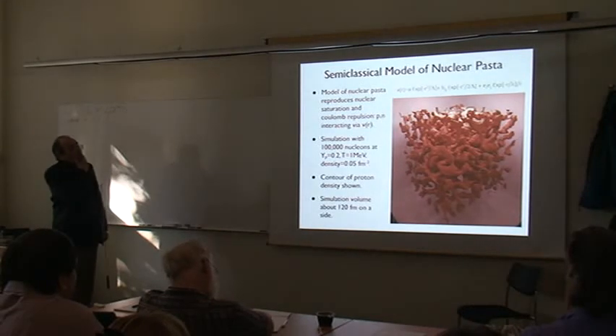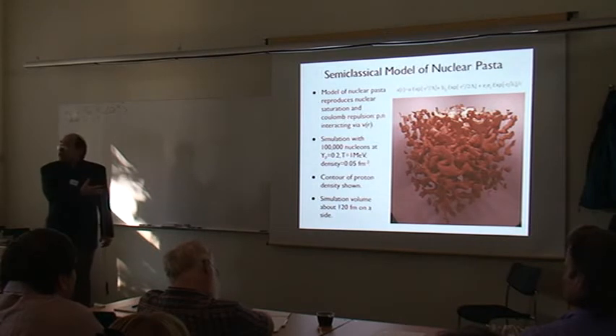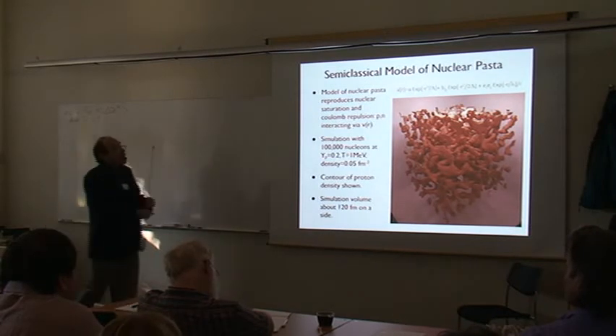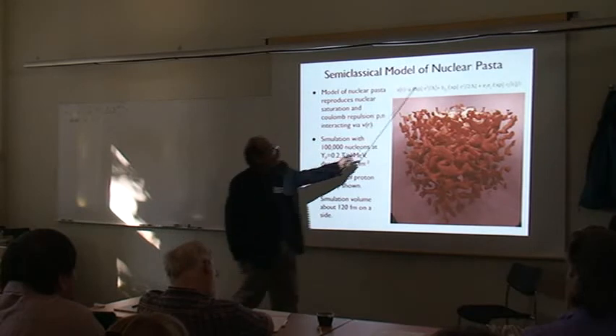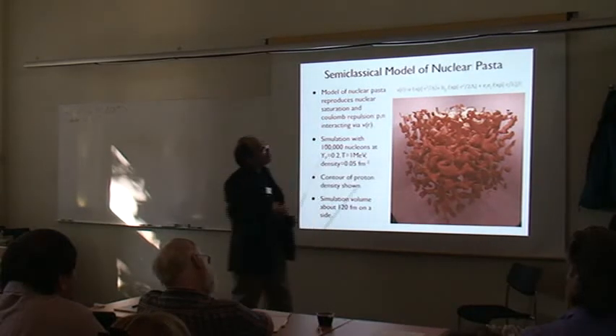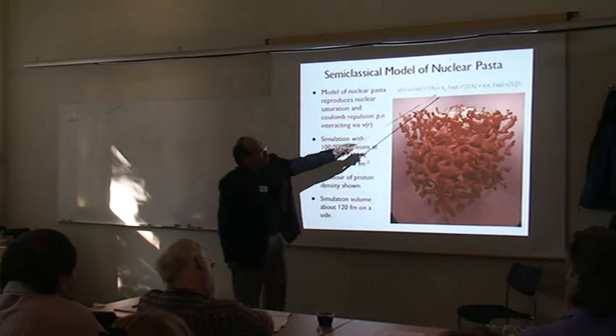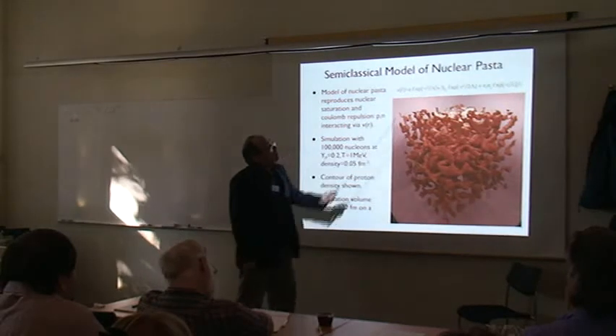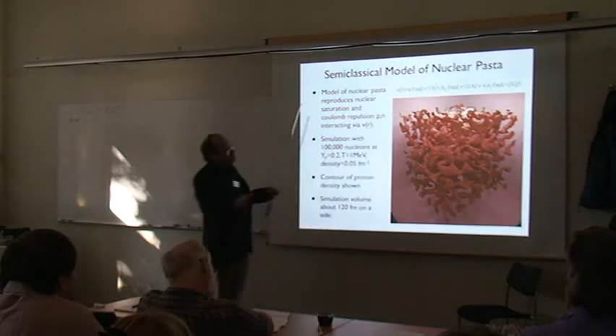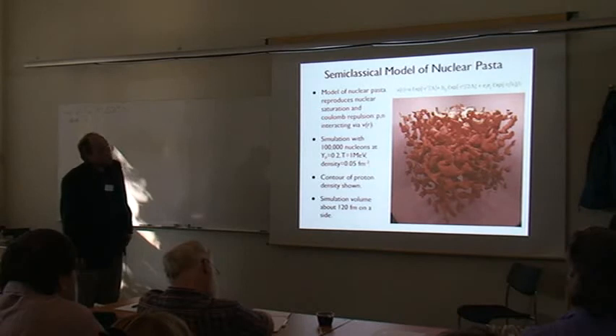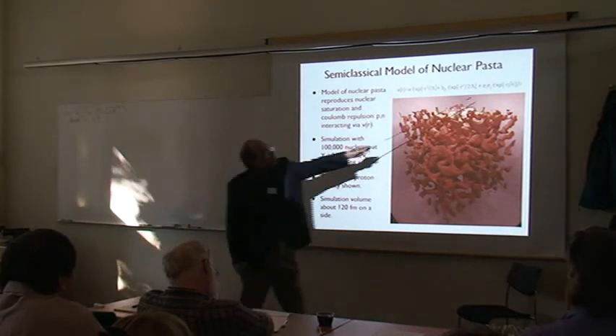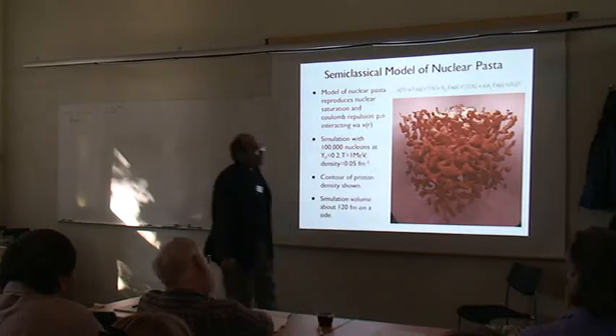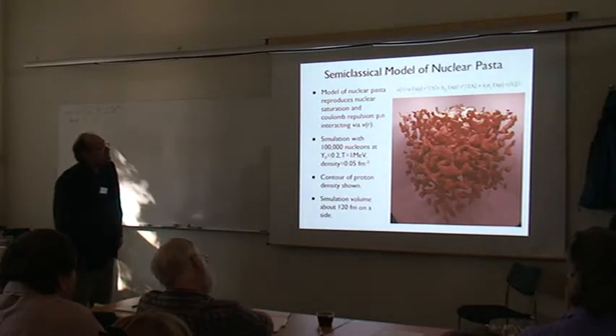So this is a simulation in the nucleon coordinates rather than in the ion coordinates, which is what I was doing before. We've got a simple phenomenological model: a short range, very short range repulsion, intermediate range attraction. The parameters are adjusted to reproduce the saturation density and binding energy of nuclear matter. And then you have Coulomb repulsion, the screened Coulomb interaction between the protons.